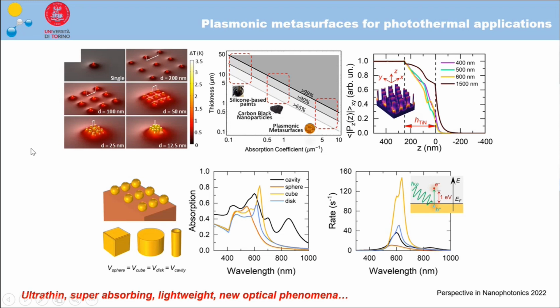On the other side, from the point of view of generating carriers and photocatalysis, here we can see that depending on the shape of the meta-atom, the single unit which creates the whole metasurface, we can have different resonances, or different efficiency in generating the carriers. We can see, for example, comparing a cavity, a sphere, a cube, or a disk in contact with titanium oxide, that we can inject many more electrons and use holes for photocatalysis when we use a cube instead of the other shapes. So we have many different degrees of freedom to manipulate light, and also chemical reactions as a consequence.